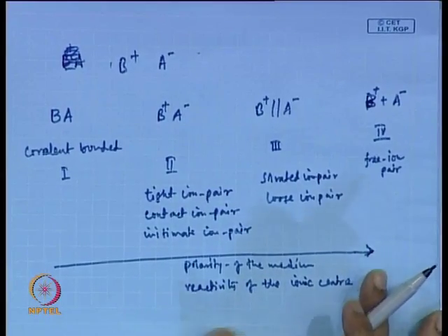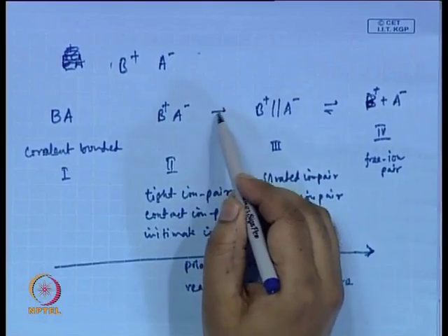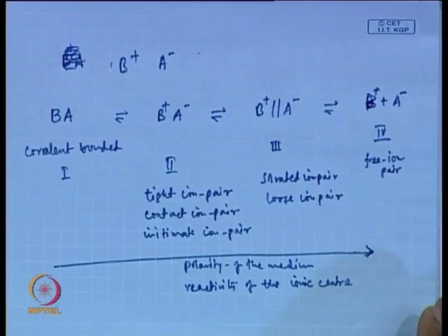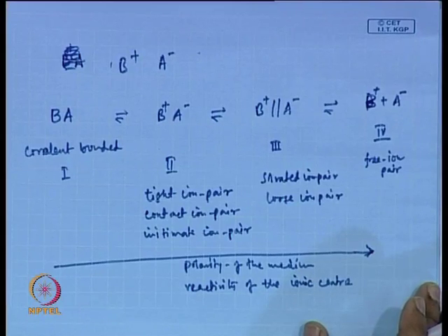In some cases these are not present in isolation; they actually remain in equilibrium, and the equilibrium shifts depending upon the polarity of the medium. So, in this way you can understand that the polarity of the solvent plays a very important role in the reactivity of these ionic reactions. If you compare with radical chain polymerization, solvent polarity has no such role to play. In radical chain polymerization, you only have to check whether the solvent can solubilize the monomers or the reagent, and the solvent should not participate in undesired chain transfer reactions. So, this type of solvent dependent reactivity was absent in radical chain polymerization.